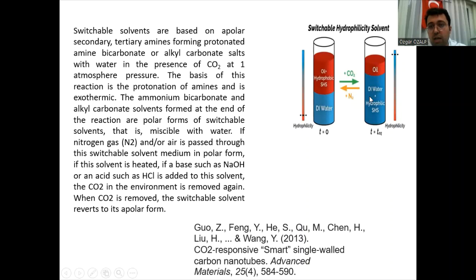For the protonated amine, we can use N,N-dimethylbutylamine. If nitrogen gas or air is passed through this switchable solvent medium, it goes to the apolar form. If the solvent is heated, or if you add sodium hydroxide, the pH is very high, and then hydrophobicity starts and the polarity changes, and palladium and other heavy metals, and organic or inorganic pollutants, are extracted into the upper phase. If you do not add anything for the polarity change, there is no extraction.